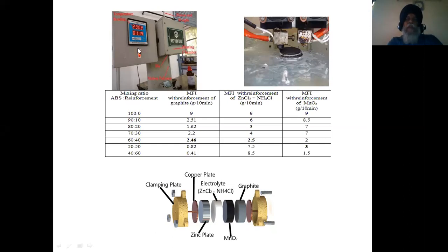So I put some thermoplastic over here, I put some load, and some wire is coming out at a particular temperature. Now you can see here there is a temperature setting of around 230, and the load is around 3.2 kg. How many grams of wire come out in 10 minutes, that is basically called its MFI. Now in this particular example, once I have a composition of ABS and graphite as 90:10, meaning 90 grams by weight ABS and 10 grams by weight graphite, the MFI value was around 2.51, right? Once I have a similar ratio for zinc chloride and ammonium chloride, it was coming out to be 6. And for MnO2, this was coming out to be 8.5.